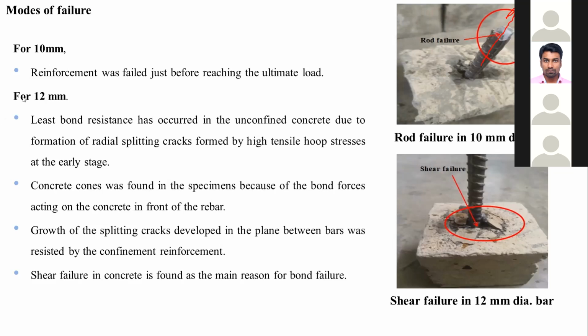If we use 12 mm reinforcement, we can find that the reinforcement will easily come out of the concrete specimen, and that failure occurs because of shear, and also bond failure occurs. We can find a cone of concrete in the specimen, which we find due to the bond forces acting on the concrete in front of the rebar.